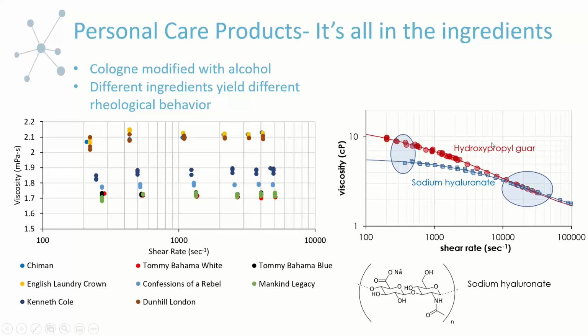And then over here, we can look at the differences between the polymer that Stacy described earlier, sodium hyaluronate, and hydroxypropyl guar, which are two commonly used polymers in eye drop formulations. And we can see that at low shear rate, they're very distinct. But then as shear rate is increased under high shear, they collapse upon each other and behave more similarly. And so this demonstrates why it's important to have a broad shear rate range when undergoing rheological tests, because you can fully understand the behavior of your formulation, based on the polymers within that formulation, and how it's going to behave under different environments.